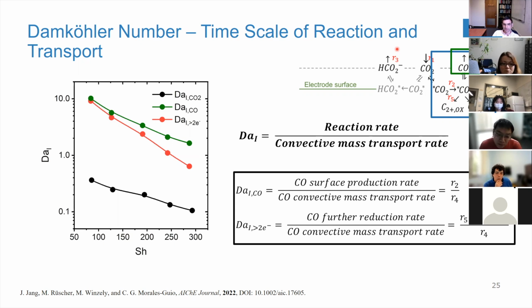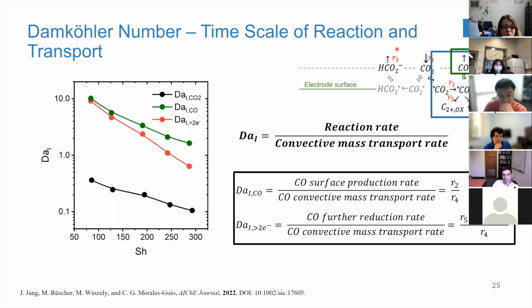Yeah, so something that we use is a boundary layer thickness to describe the mass transport. What that means is how far the bulk of your electrolyte concentration is from the surface of the electrode. And here, when we change the rotation, we can change that boundary layer. It's just a relative number, but between 100 micrometers maybe to 20 or 30 micrometers. So if you rotate very fast, the boundary layer is maybe 20 micrometers, so the bulk of your electrolyte can come as close as 20, 30 micrometers. In a gas diffusion electrode, those distances could be 1 micrometer, or maybe less, nanometers really, because you actually bring that interface between the gas and the liquid together at the interface. So if we rotate the electrode between 100 RPM and 1,000, 2,000 RPM,